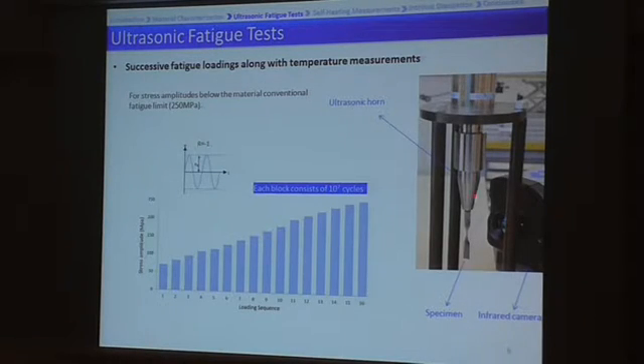So here you can see the experimental setup used in our study: the ultrasonic fatigue horn, the hourglass-shaped specimen, and also an infrared camera that we used in order to capture the temperature on the surface of the specimen during the test. In order to study the self-heating behavior of the material, we did successive fatigue loadings with increasing stress amplitude. All of the tests were tension-compression with the ratio of -1.